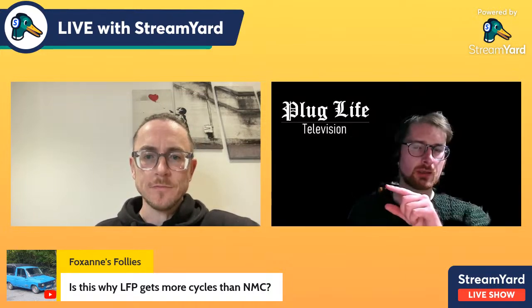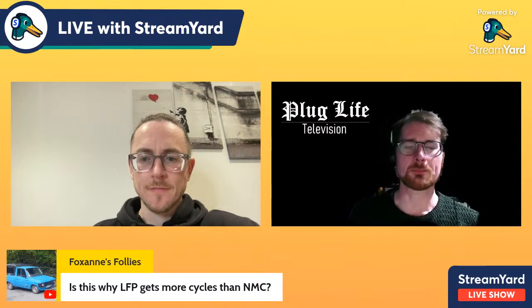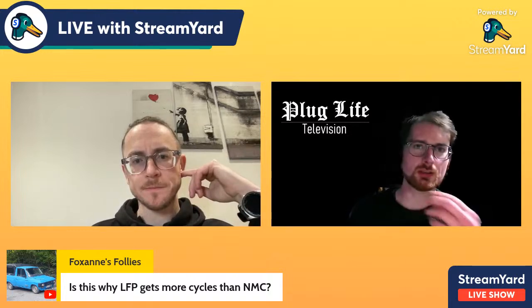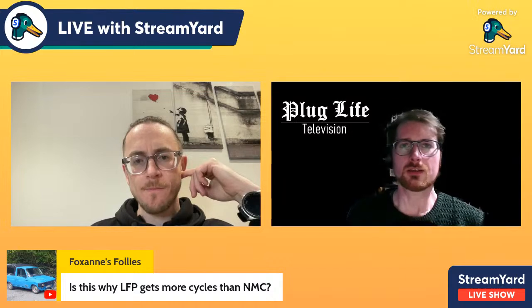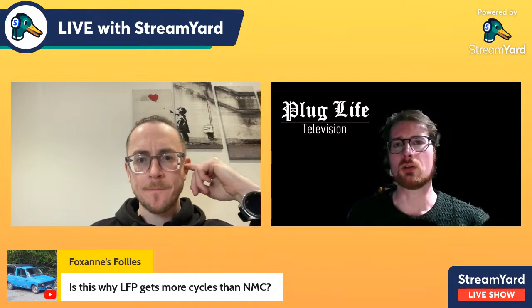Really impressive. We've got a question here from Foxanne's Follies. Is this why LFP gets more cycles than NMC? Oh yeah, so that will be to do with the maximum potential of the actual cathode material itself, the LFP versus NMC. That'll inevitably be part of it, because you've not got that loss of electrolyte and that loss of lithium inventory, it's called, because the lithium again gets mixed up in that degradation as well. Plus, LFP is a totally different structure from NMC. It's not like you just swapped some elements out. It's a physically different structure, an olivine structure versus NMC that's not olivine.